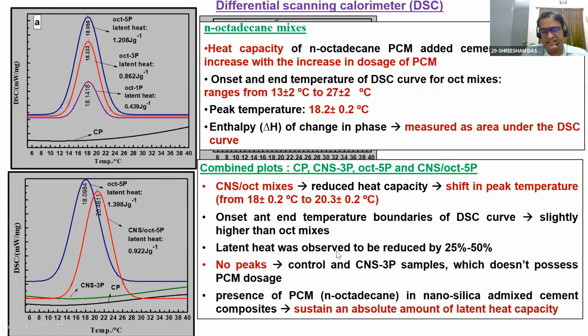But we have realized the latent heat was observed to be reduced by 25 to 50 percent. So it is fine. When I'm adding the nanoparticles, the heat absorbance is reducing, but it is not reducing to zero. It is able to absorb a substantial amount of heat. So you have to choose. You need either just a PCM based material, that is giving me very low strength, or a nanoparticle admixed PCM based material that is going to give me sufficient compressive strength, which we civil engineers normally go mad about, as well as the latent storage capacity.